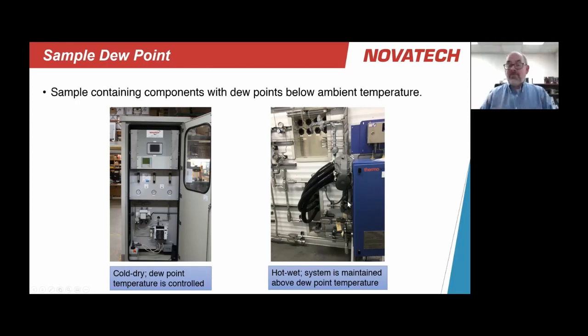Or the other approach is I stay away from the dew point. If my dew point temperature is 70, I can simply run everything hot well beyond the dew point temperature to ensure that everything stays as a gas. 70 degrees C dew point temperature, maybe I run everything at 130 degrees C. I bring everything in heated sample lines, a heated sample valve going into a heated analyzer so that I'm never near the dew point temperature and I have no risk of condensation. Two different approaches with pros and cons. This may be more complex, but I haven't altered my sample in any way. Whereas a cold-dry system, while relatively simple to implement, alters the composition of my sample gas. If 30% of my sample was water and I take out the vast majority of it, I have greatly increased the concentration of all the other components that the analyzers see. I have to be able to correct for that.